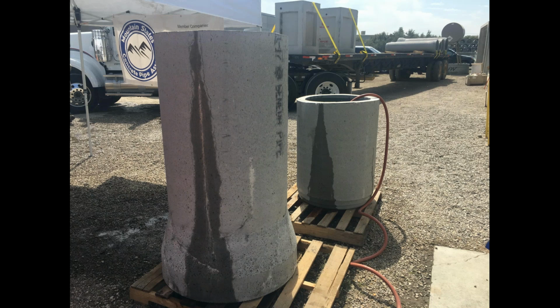By the time we let this thing sit for another couple of months, it was completely sealed up and didn't leak any water. The one furthest from us that we had just filled up that morning, that was just brand new, was leaking at a rate of about 1 inch per minute, roughly. It was coming out pretty quick. So it's a pretty significant difference. We had to keep that hose in there and keep it turned on to even keep it up, so that it would balance it out.